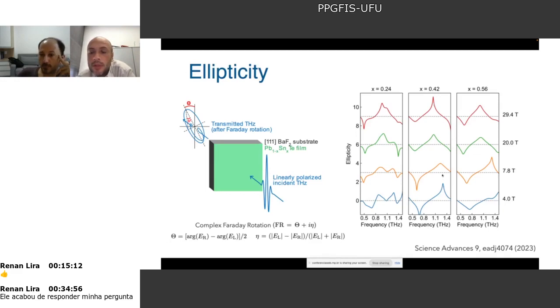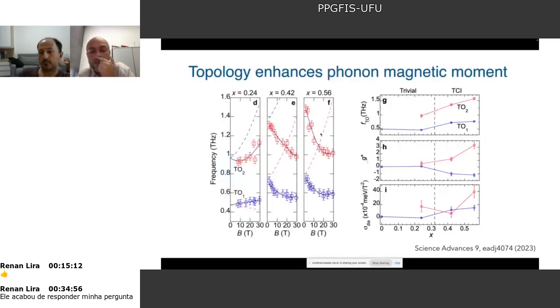And with magnetic field, you can see that the ellipticity peak changes in frequency, right? Here it is much clearer: with increasing magnetic field, the frequency decreases. And if you plot the peak of ellipticity as a function of magnetic field, then you can fit it and obtain these three parameters: the frequency of the TO phonon, the phonon magnetic moment, and the diamagnetic shift.